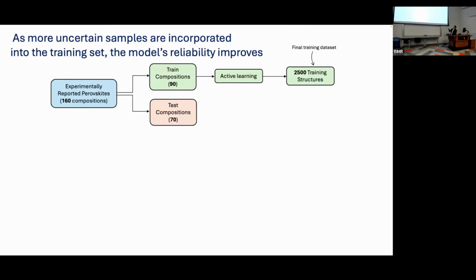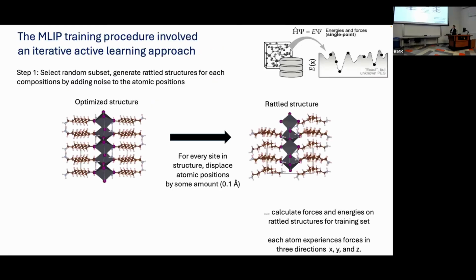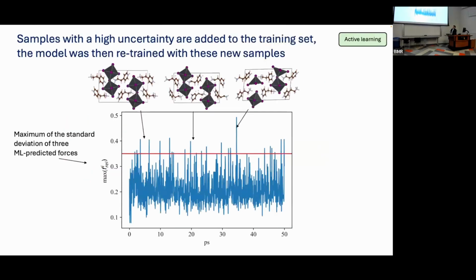With the training compositions, we perform that active learning loop. And eventually we get to a large training set after exposing the model over and over to cases where it had failed. So for the initial set, we start from the optimized experimental structures and we displace the atoms like I mentioned before. We add Gaussian noise based on the sites to each site in the unit cell. We calculate the energies and forces of these structures.